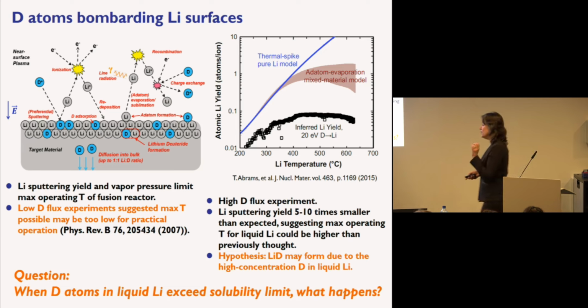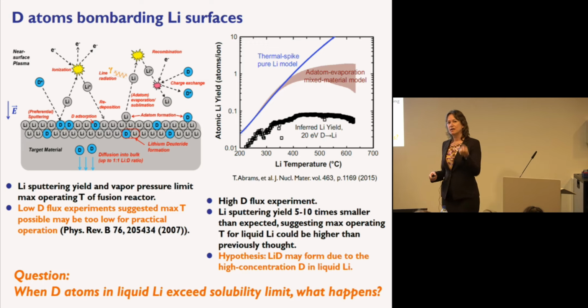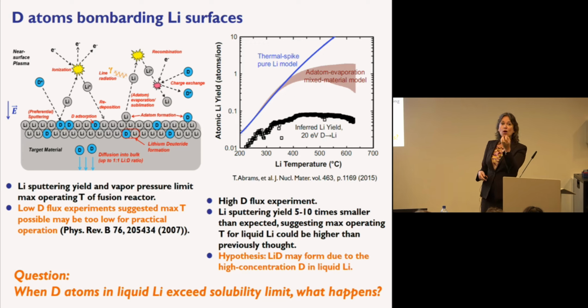I should say that when you make lithium deuteride, it melts at a much higher temperature than lithium melts at. And so what that means is that when you're at a lower temperature, you should start to nucleate small solid particles of lithium deuteride in the liquid lithium. And I'm not going to show you all the data for that, but we in fact do see that.